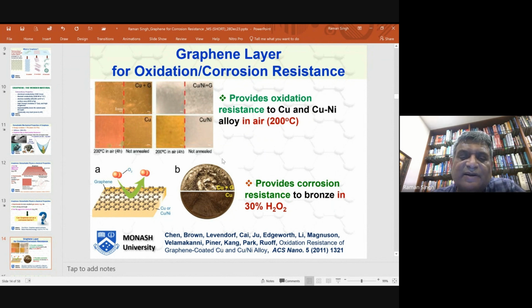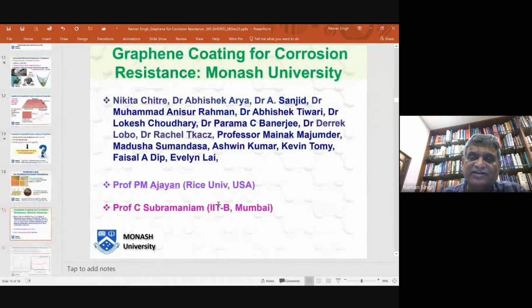They did another experiment where they took a penny, and the upper half of the penny was coated with graphene, and they dropped the entire penny into a highly oxidizing hydrogen peroxide environment. You can see that the upper half did not undergo any corrosion, no tarnishing, no corrosion. The lower half, which was not coated with graphene, did undergo tarnishing.